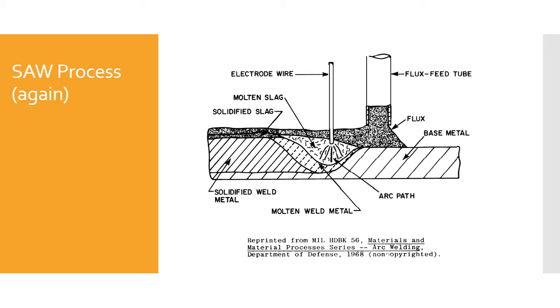All currents and polarities are used, depending on the desired penetration, bead shape, and whatnot. Reverse polarity provides the best bead shape and penetration, while straight polarity gives higher deposition rates but less penetration. Alternating current provides penetration somewhere between the two and is preferred for multiple wire welding setups. The fused flux is chipped off the weld and discarded. So, giving you a couple of different spins on this, things I've pilfered from, like I said, mil-spec handbooks on welding, Army manuals, Navy manuals, but that's the gist of the process.